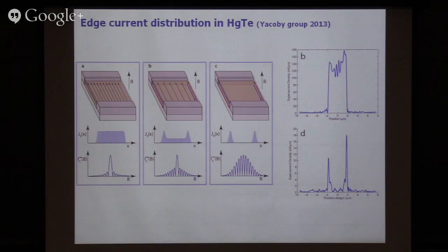But more recently, there are more microscopic imaging techniques, some done by my colleague Kathryn Moler, and I'll just show data by Amir Yacoby. So you take this quantum spin Hall insulator, mercury telluride, he got a sample from Würzburg, but then put superconducting contacts here, and then subject it to a magnetic field. So you see superconductivity come in here in a very interesting way. Then you measure the Josephson current across these two superconductors, mediated by this topological insulator state. So as you dial the magnetic field, you can measure the different Josephson current as a function of the magnetic field.